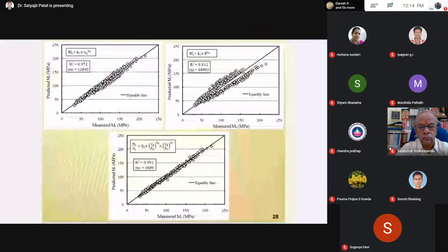The 3 parameter model demonstrates the effect of sigma 3 and sigma D separately. In the first model, it did not consider the effect of sigma 3. But in the 3 parameter model, the effect of sigma 3 and sigma D is clearly separated by the parameters K6 and K7. So from this study, it has been concluded that the 3 parameter model fits best for predicting the resilient modulus for this cemented base material.